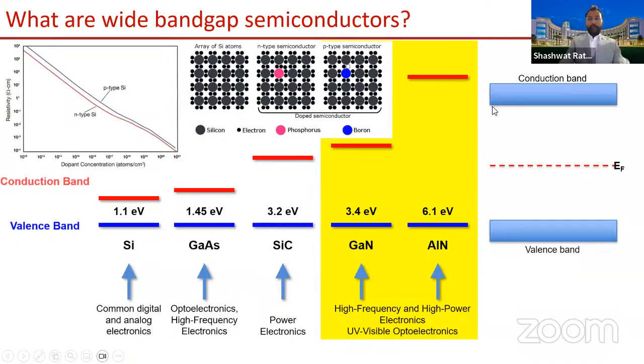So essentially what happens is, in an undoped semiconductor, you have the Fermi level, which is the average energy of electrons in semiconductors, at mid gap. Now, when you dope the semiconductor, you create these energy states which are close to the conduction band. These are sufficiently close such that at room temperature, you excite enough carriers so that your Fermi level also moves close to the conduction band. And this is how we achieve conductivity in silicon.